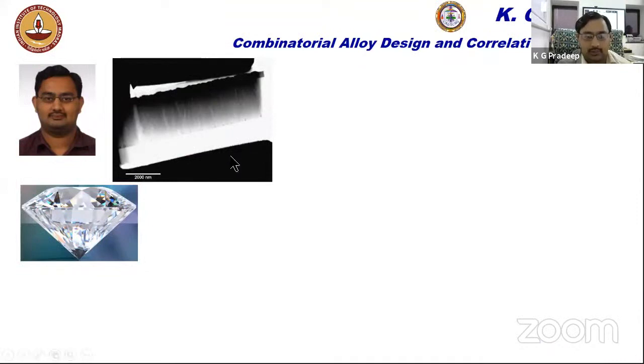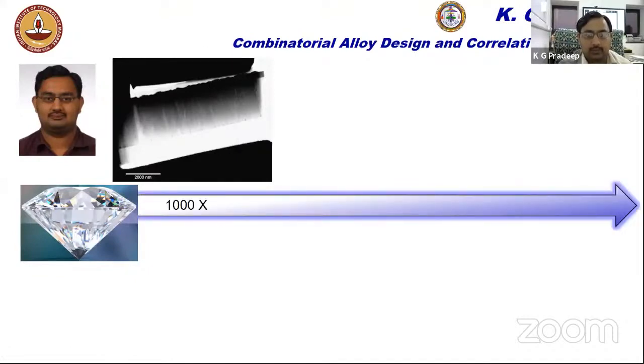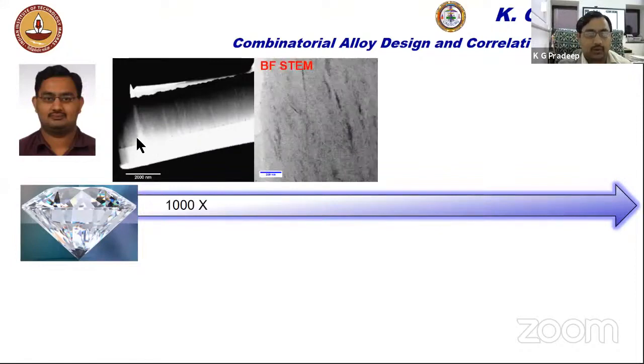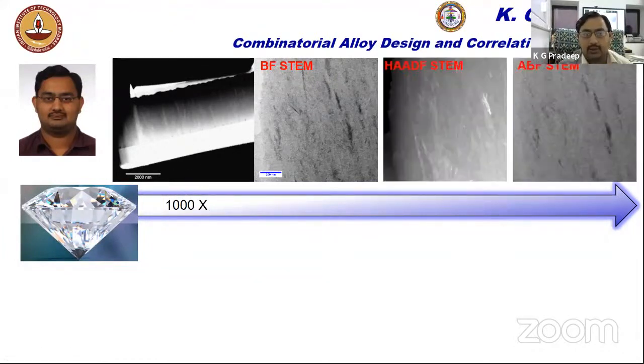If you now look at, let's say, a reasonable scale, this is a thin film image obtained in an electron microscope after it has been prepared, for example, with focused ion beam milling to get it electron transparent. The first image starts with 1000x magnification. That means if you magnify something 1000 times more than what your eyes can see, this is the film that you see. Now, if you go a little bit higher in magnification, you start revealing many things. In the bright field image, you start seeing the darker contrasts, which are those defect sites, at approximately 10,000 times magnified from what your eyes can see.